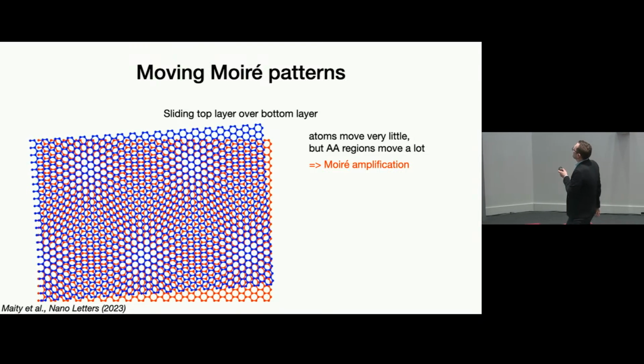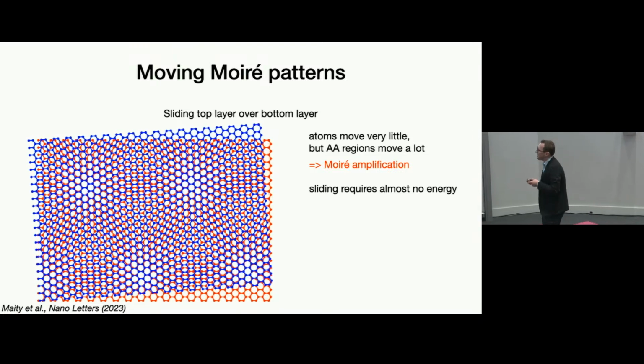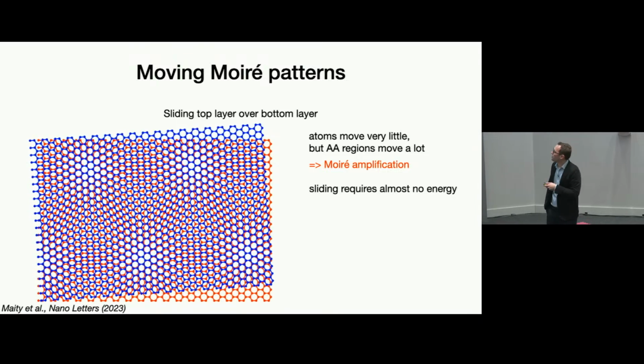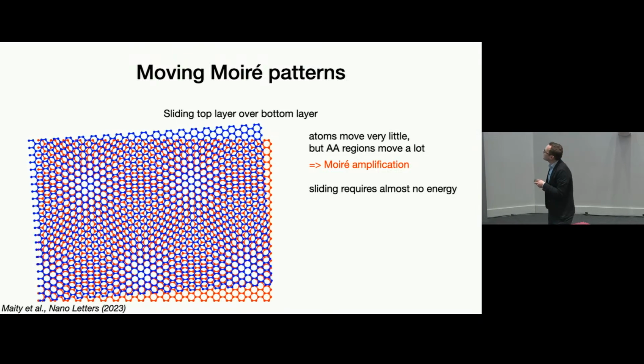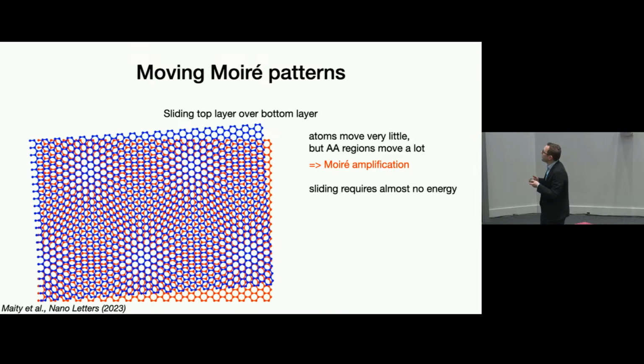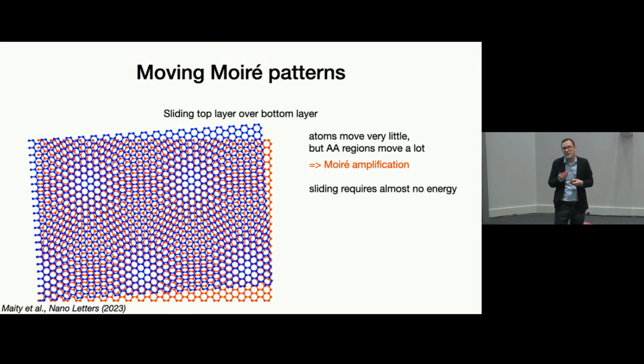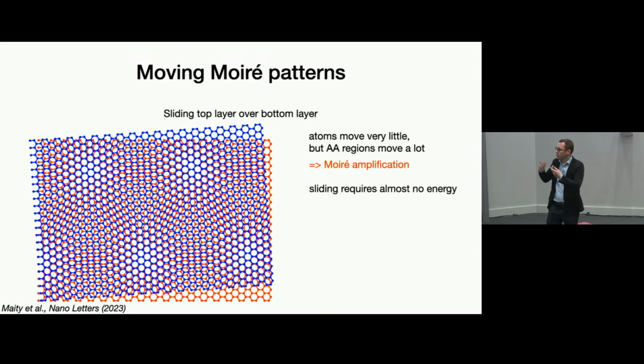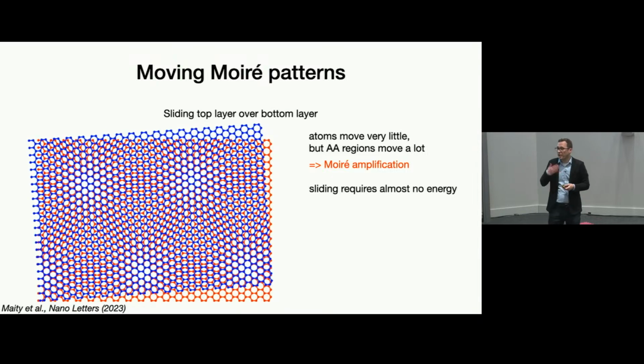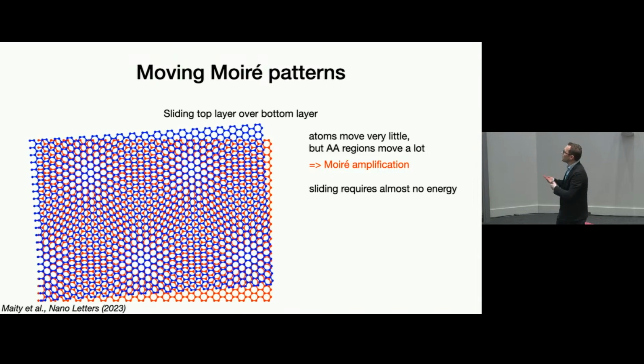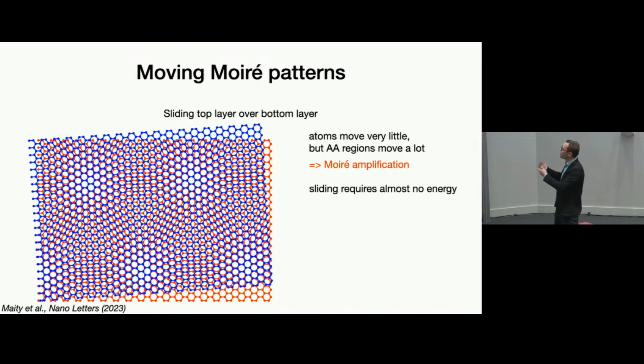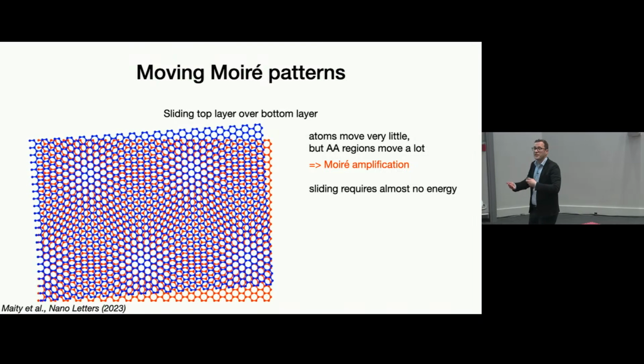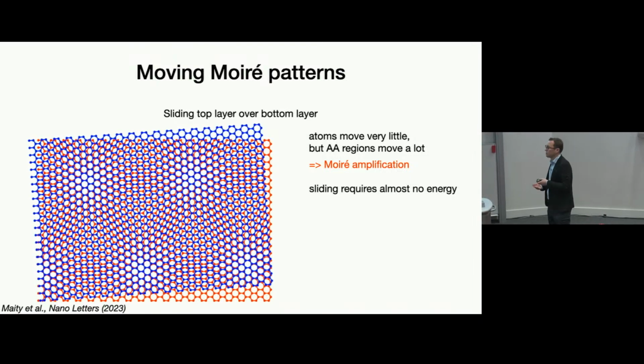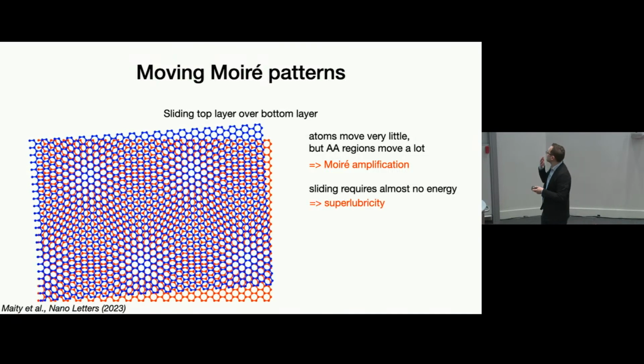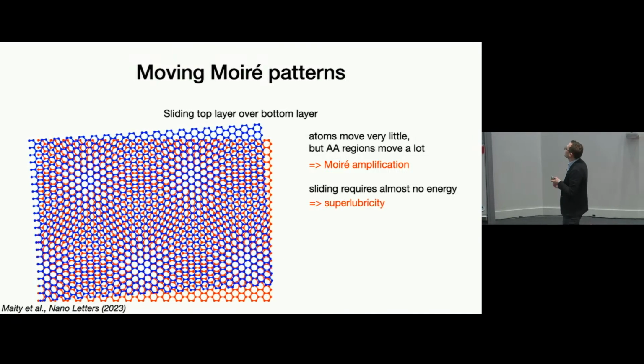The second observation is that this sliding actually requires almost no energy. And this is because in some regions, as you slide, the atoms move from a low energy AB stacking to a high energy AA stacking, so that costs energy. But in other regions, the opposite happens, and so you gain energy, and so the net energy requirement to slide is almost zero. And this is something called superlubricity.